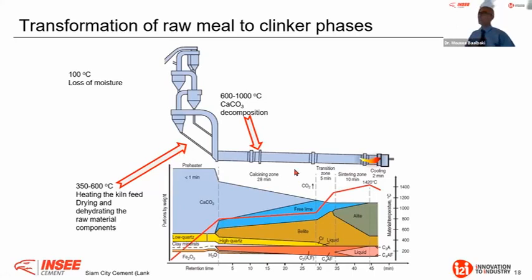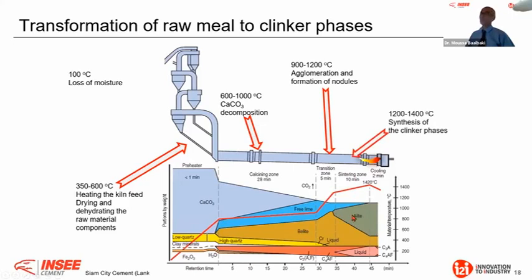Therefore, after that, the calcination zone, it will go to what we call a transition zone, where we start to form the nodules, the clinker nodules. We have agglomeration, the temperature goes up to 1200, and from there, you see that most of the free lime will combine with the C2S that we call the belite, I will come to that later, to form what we call C3S. And these are, we see at the end, the 4 main constituents of the clinker that I will discuss. They are the silicate phase and the aluminate phase: C3S, C2S, C4AF, and C3A.